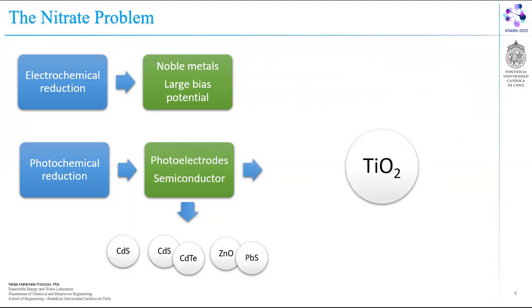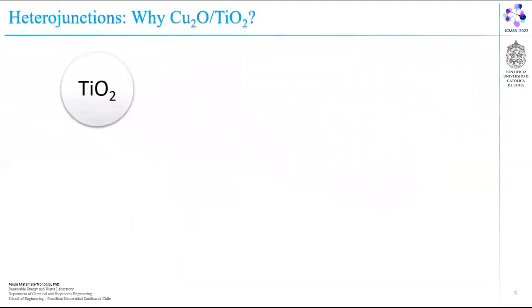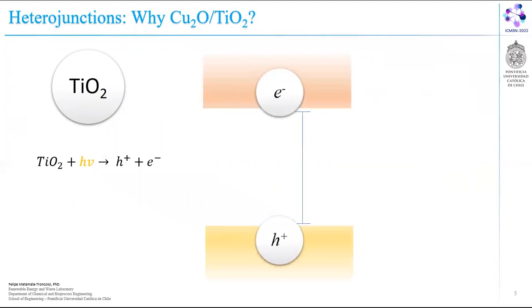used extensively to produce solar devices and power plants because it has low cost, low toxicity, high chemical stability, and obviously commercial availability. Titanium oxide can absorb light radiation, generating a photoinduced electron-hole pair. Then the photoinduced electron can jump from the valence band to the conduction band, leaving a hole behind. And this pair can then participate in reduction and oxidation reactions respectively.